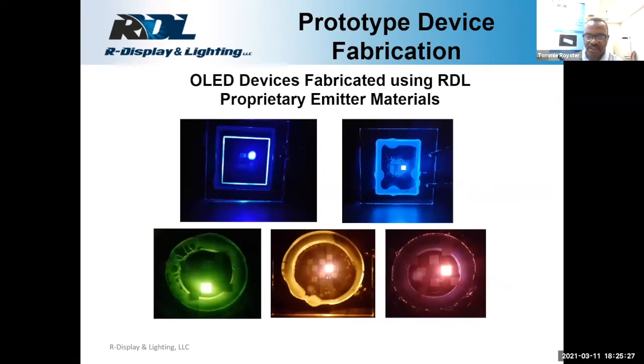Shown here are examples of prototype devices fabricated using our proprietary emitter materials. The top left material was fabricated using a phosphorescent blue, and the material on the right is a newly developed charge transfer emitter. All the devices on the bottom were fabricated using standard phosphorescent emitters.